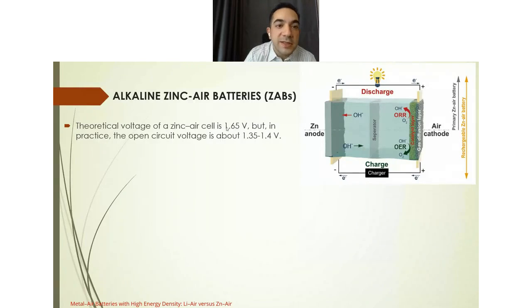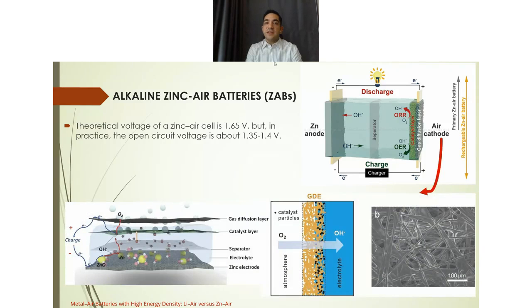So moving towards introducing zinc air batteries, they have a theoretical voltage of 1.65 volts, but in practice, due to a number of reasons, their OCV is usually about 1.35 to 1.40 volts. This can be due to the sluggish kinetics of the oxygen reduction reaction, which I will explain shortly. As I stated earlier, zinc air batteries use an air cathode, which allows oxygen from the ambient air to penetrate through a porous structure of the air cathode into the system. The air cathode usually consists of two layers: the gas layer, located at the outer surface, and the catalyst layer, located at the inner surface.